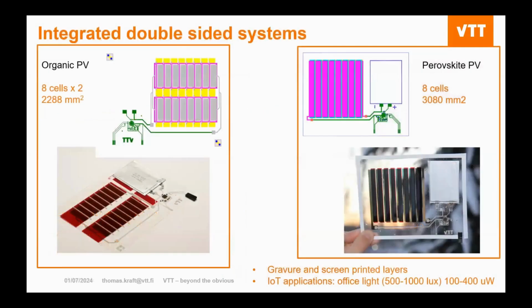In our case, we tested it both with organic photovoltaics and perovskite photovoltaics. With the OPV, you can see we used a P3HT-based active layer with both PCBM and ICBA. These are different fullerene derivatives, if you're not familiar. And then for the perovskite, this is quite a nice work. This is a flexible perovskite, and we actually won an award two years ago at the Munich LOPEC conference. It won the best demo award for this particular field. And of course, we can go into more detail if you're interested. But the point is just to show you the use case.